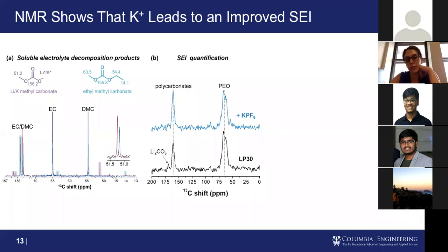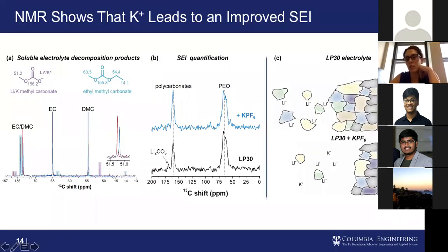So what this is basically telling us is that when we have KPF6 present, we don't have as many soluble electrolyte decomposition products, and we have more ionically conductive species in this SEI layer, which is probably helping our lithium ion transport to the surface of the anode.